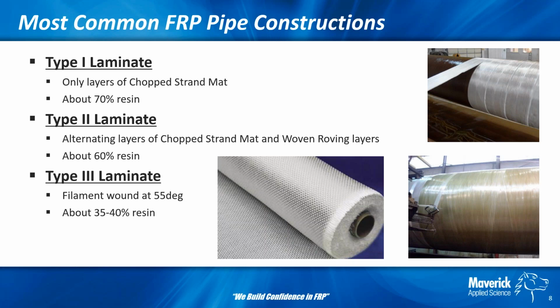Just a very quick background, so you know a little bit of what I'm talking about here, if you don't have the FRP background. When I mention type 1 laminate, that means it's only layers of chopped strand mat. It's very high resin content, about 70%, which means 30% glass content. Type 2 means alternating layers of mat and woven roving. The picture on the left there is a woven roving. This has slightly higher glass content, at about 40%.